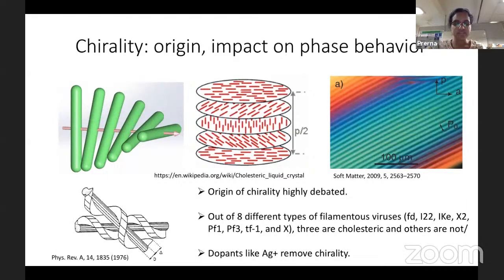The reason these viruses behave as chiral objects is highly debated. Nobody really knows whether it is the fact that the proteins are helically wrapped that is leading to the chirality, or the charge distribution, or something else. And people know how to change it by adding dopants and things like that. But the general idea of why hard rods, or hard screws here, should twist is that you should think of them as screws essentially. If you have two screws and you want to increase the free volume, or in other words, decrease excluded volume, you would want them to sort of intergroove with each other by coming at an angle.